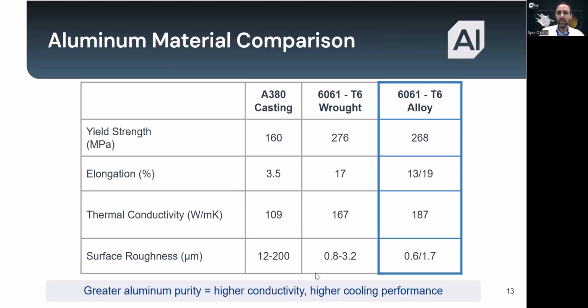So in terms of mechanical properties, we're right in line with what designers expect. Yield strength and elongation that track very closely with wrought material, which means no compromise in structural performance. Here's where we stand out. Because our process stays very tightly within the 6061 alloying specification, our material carries significantly higher aluminum content compared to many wrought products. That results in a higher thermal conductivity of 187 watts per meter-kelvin versus 167 watts per meter-kelvin for wrought material. This translates into 12% more conductivity than the wrought material itself. So for defense and high-performance applications, that extra conductivity is a real advantage.